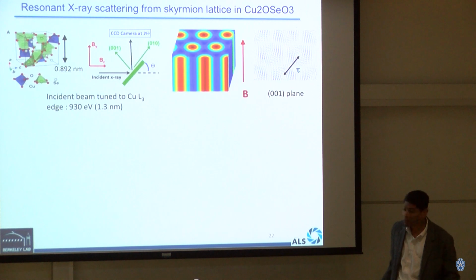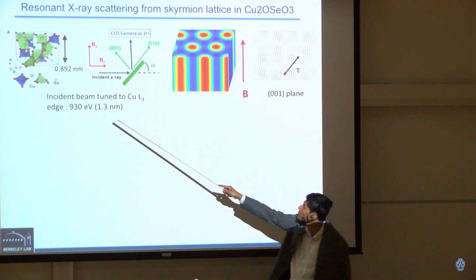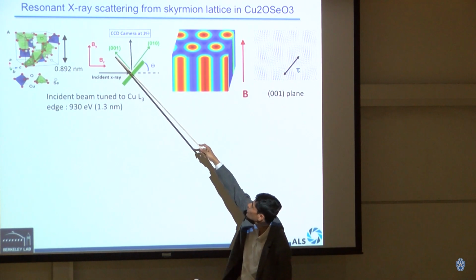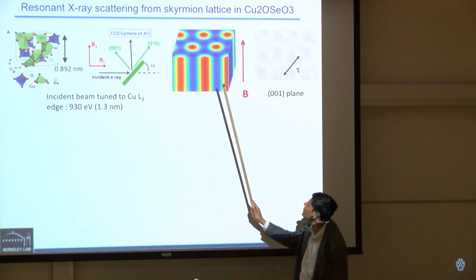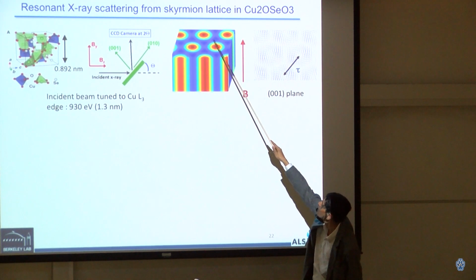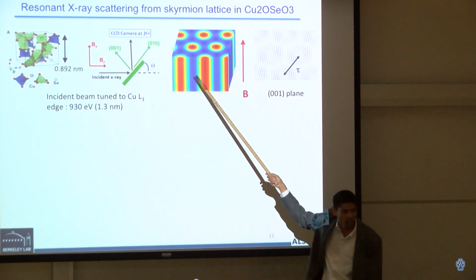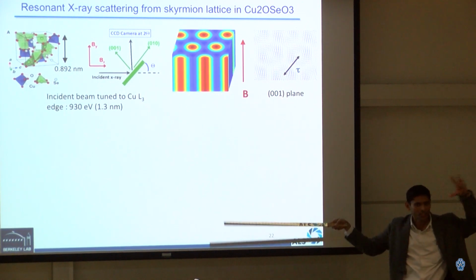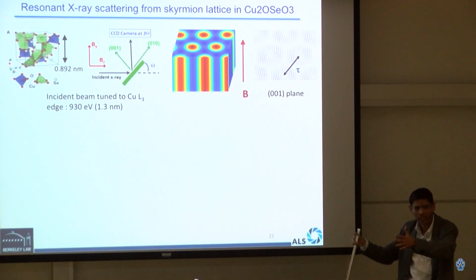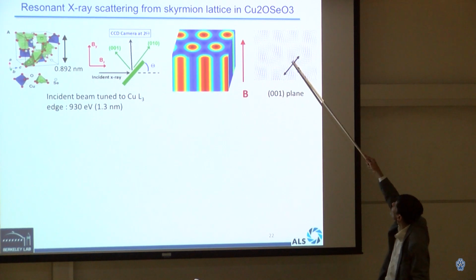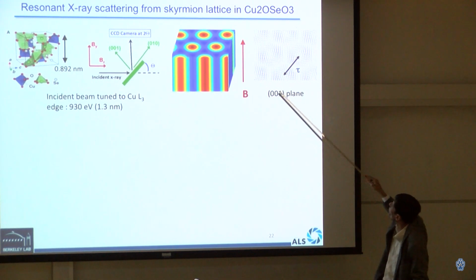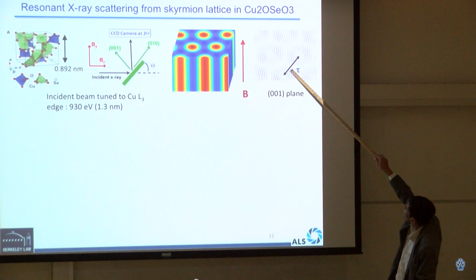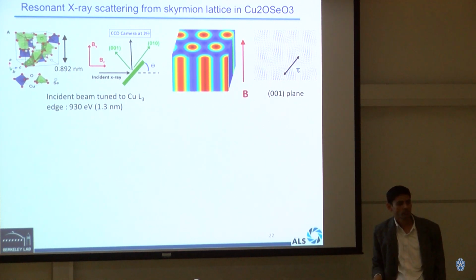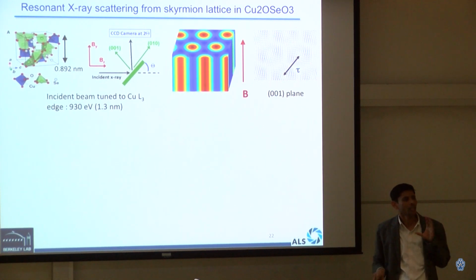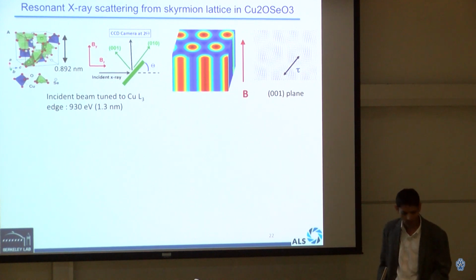So let's do that on our copper oxyselenite sample. This is back again as a sample. It will be aligned so that the 001 is into the detector. We will apply a magnetic field, and then that's how the skyrmions will form. And if you are an X-ray, let's imagine that you are an X-ray looking at this material, then you will see these spin swirls in the Bragg plane with a reciprocal lattice distance of tau. Let's do that experiment. Let's get the crystal, let's align it, and let's see what we see.